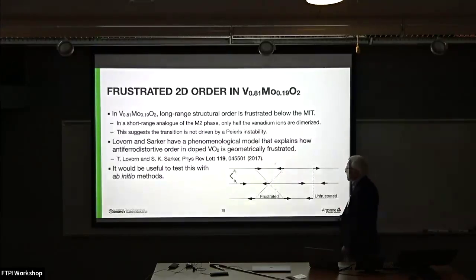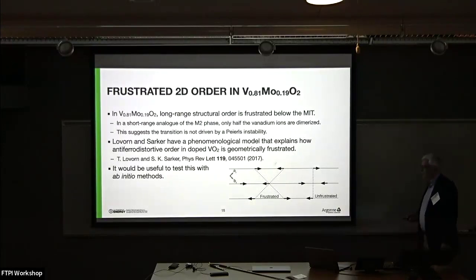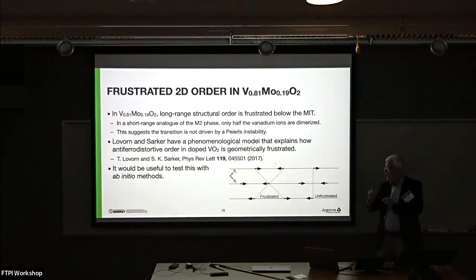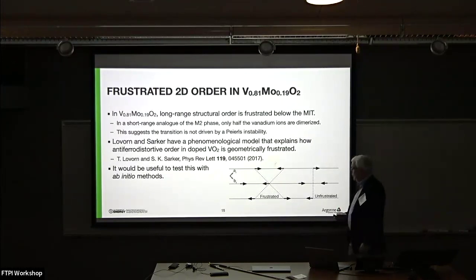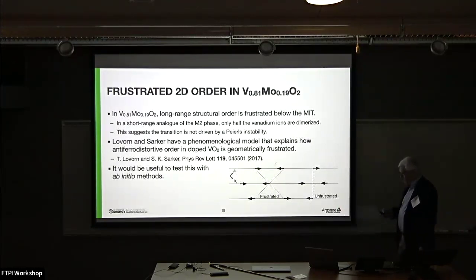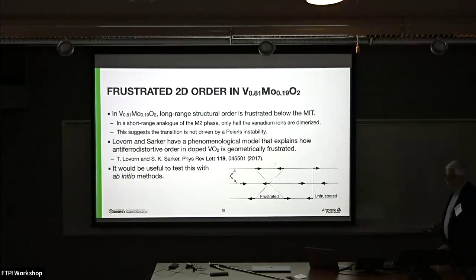Okay. It turns out this is actually a kind of geometric frustration. If you have the buckling, for instance, in one plane, the neighboring planes, it's degenerate, it's only the nearest neighbor plane. They don't know whether to go one way or the other, and so you get very weak correlations. You have to have longer range correlations in the orthogonal direction to generate long range order, as you see in the M1 phase. Okay, so that's a VO2 example, and I'm sure that these things would give valuable information on a lot of other such electronic phase transitions.